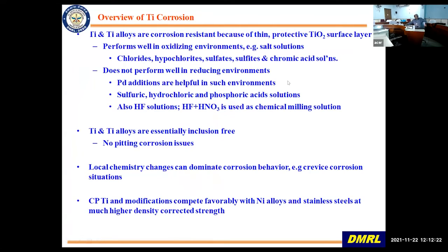Now, as I told, the thin protective layer of TiO2 that forms on the surface protects it, but it is good in oxidizing environments, that is in chlorides, hypochlorite, sulfates, and chromic acid solutions, but is not as good in reducing environments like sulfuric acid, hydrochloric acid, phosphoric acids, etc. And in order to improve it, you can do palladium additions, which increases the corrosion resistance.